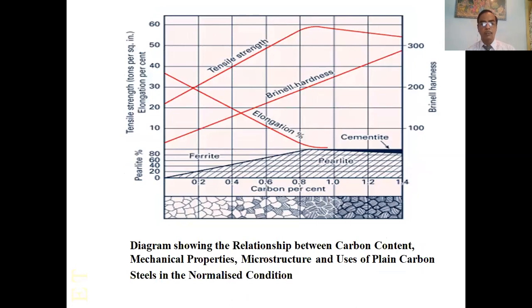There is a diagram showing the relationship between carbon content, mechanical properties, microstructure and uses of plain carbon steels in the normalized condition. This portion is pearlite, and this is ferrite and pearlite. This is basically carbon content, 0.2, 0.4, 0.6, 0.8. And this portion is cementite. As the carbon percent increases, elongation decreases, but brittleness and hardness increase. Hardness increases as the carbon percent increases. And the tensile strength also increases up to a point of 0.8 to 0.9. After that, it decreases to some extent. This is the relationship between carbon content, mechanical properties, microstructure, and use of plain carbon steel in the normalized condition.